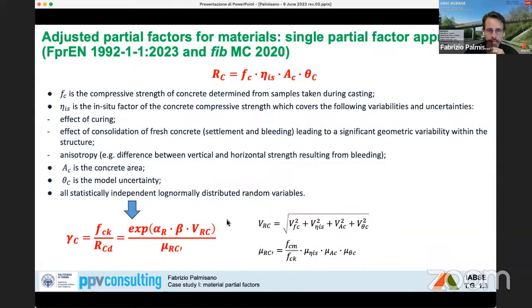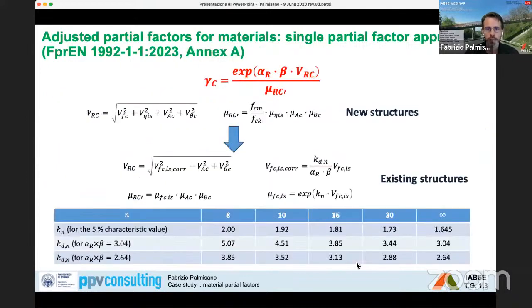And the expression is an exponential function of the sensitivity factor, which for a dominant variable we can assume equal to 0.8 for resistance, the target reliability index beta, which in this case will be equal to 3.8, the coefficient of variation of RC, which is a function of all four parameters, and the bias factor of RC, which is a function of all parameters. However, this formulation is correct for new structures when we assess the FC, the FCK. For existing structures, we assess the in situ value. So a